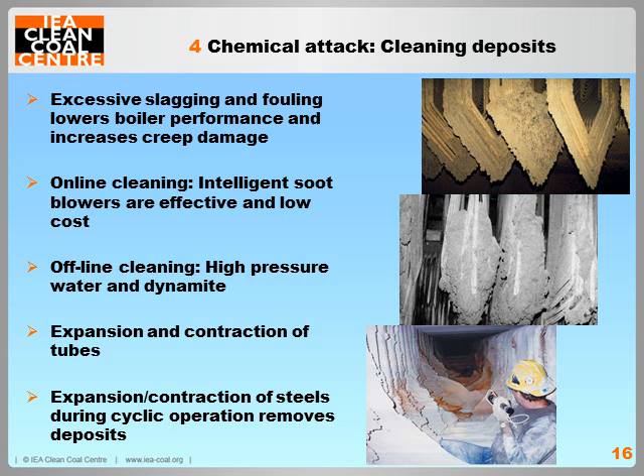Excessive slagging and fouling will increase creep damage as well as reduce boiler performance. Soot blowers use compressed air, steam or water to knock off deposits. New intelligent soot blowers are retractable, can vary the injection pressure and use heat transfers to determine when cleaning is required. This combination allows for maximum cleaning, minimum resource usage and minimum material damage.